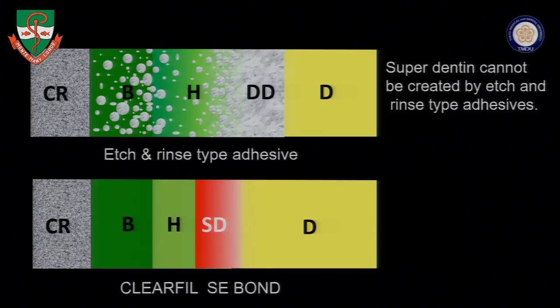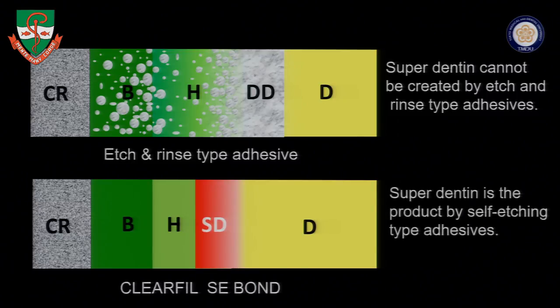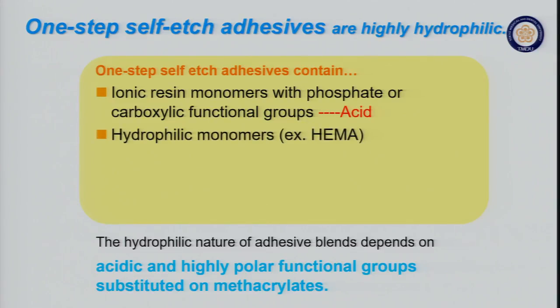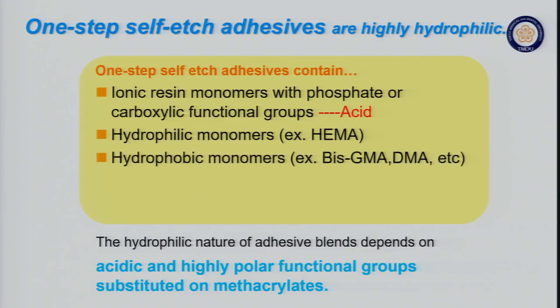Unfortunately, the superdentin is the product in the case of the self-etching material. In the case of etch and rinse technique, the superdentin cannot be created at the moment. In the case of one-step system, this is designed to be very hydrophilic because the bonding resin itself has to etch the enamel and dentin surface. Of course, the source of the acid is the adhesive resin monomers. And the hydrophilic matrix resin monomer is included, like HEMA, and hydrophobic monomers are also included in the bonding resin to make the bonding resin layer very strong, mechanically strong.